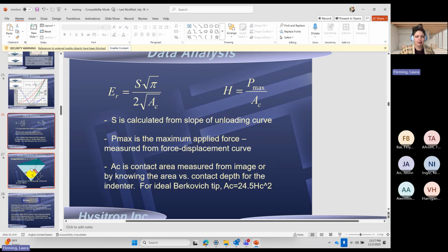For an ideal Berkovich probe, so Berkovich is kind of the default tip for nanoindentation. The rule of thumb is if you can use a Berkovich, you can. It's a very specific pyramid, three-sided pyramid with a very specific angle. If we went back to 8th grade geometry, I'm sure we could figure out how to do that calculation. You go down the pyramid and you cut it and you look at how far down you went versus what the area is, and you can make a relationship. For an ideal Berkovich, that contact area is 24.5 HC squared.